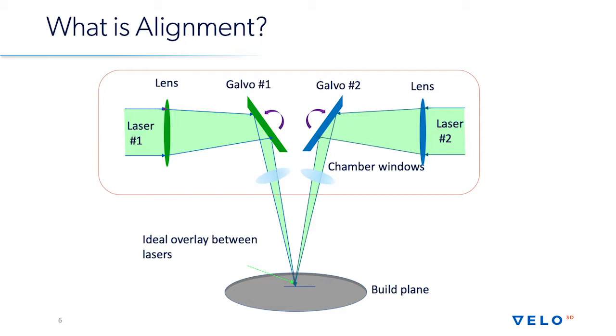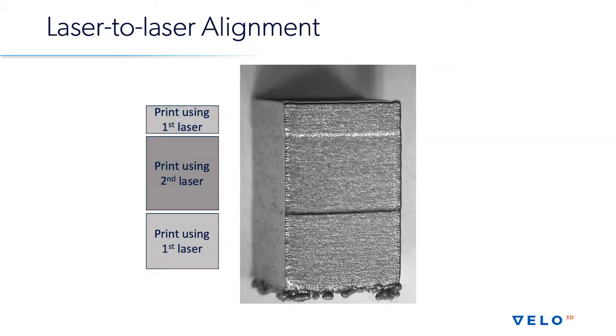So what happens if it's not? This is an example of a stacked cube print that we like to do to validate overlay. Essentially what we're doing is building a block with one laser, and then after a certain Z height, building a block with a second laser, and then going back to the first laser, and you can do this throughout the entire Z height and characterize, at least somewhat quantitatively, overlay mismatches. In this particular case, what we did was turn off the thermal control of the system. So we're not running an intercooler, we're not maintaining gas flow temperatures, we're just letting it run.